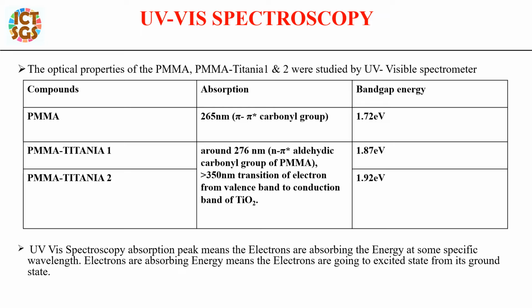UV visible spectroscopy. The optical properties of PMMA titania 1 and 2 were studied by UV visible spectrometer. The UV visible absorption at 265 nanometer indicates the pi to pi star transition of the carbonyl group of the synthesized PMMA. The other absorption of the PMMA titania nanocomposites occurs around 276 nanometer, indicating the n to pi star transition of the aldehyde carbonyl group of PMMA. The transition above 350 nanometer is the transition of electrons from the valence band to the conduction band of titania.